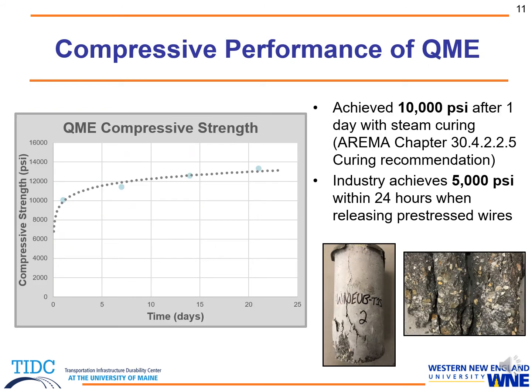This is our compressive strength analysis of mix QME. So we achieved over 10,000 psi after 1 day with steam curing, and this was done to mimic the steam curing practice in the field that's used by the pre-stressed concrete industry. So what we did was we put it into our curing oven at a temperature of 70 degrees Celsius before we tested after 1 day.